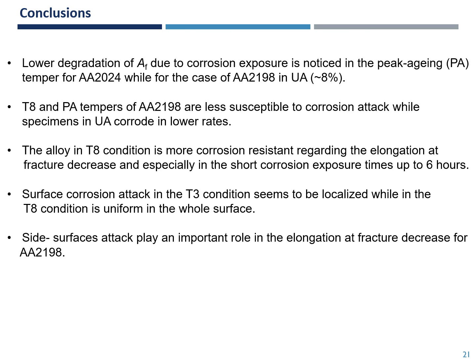The main concluding remarks of the present work are that lower degradation of elongation fracture due to corrosion exposure is noticed in the peak aging regime for aluminum alloy 2024, while for the case of aluminum alloy 2198, the lower degradation of elongation fracture due to corrosion exposure is noticed in the under-aging condition. T8 and peak aging tempers of aluminum alloy 2198 are less susceptible to corrosion attack, while specimens in under-aging temper corrode at lower rates. The alloy in T8 condition is more corrosion resistant regarding the elongation fracture degrees, especially in the short corrosion exposure times up to 6 hours.